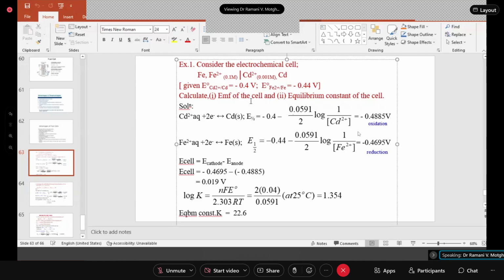So cadmium has an E naught of minus 0.4, whereas iron has an E naught of minus 0.44. So we expect that this is a greater negative value, so oxidation will take place at a greater negative value. So before we go, whether oxidation is taking place here, is it really a left-hand electrode acting as anode? We will verify by calculating the E half values for each of them. So E half for cadmium is calculated, comes out to be minus 0.48, and E half for this particular electrode comes out to be minus 0.46. So looking into the potential values under such concentration conditions, we say that oxidation is taking place at the cadmium electrode and reduction taking place at the iron.